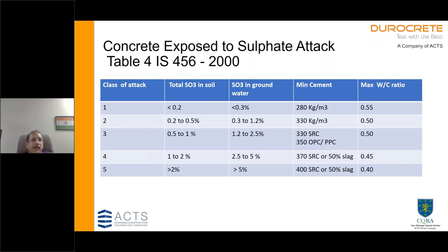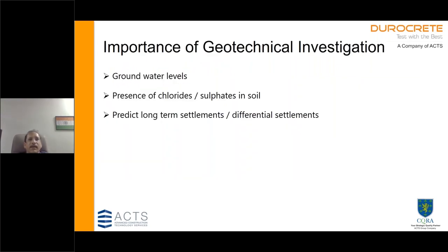Now many a times we find that there is a geotechnical investigation report, but the class of attack and the grade of concrete and the maximum water cement ratio is not taken in conjunction with the soil investigation report. If the SO3 content is between 0.5 to 1, they recommend either a sulfate resisting cement or OPC or PPC. And generally, if you are having a very high class 4 or class 5 level of sulfate attack, you need to either use a sulfate resisting cement, or if there's a possibility of a chloride attack, you should replace at least 50% of cement by slag and not use SRC. So these are the things that we need to look at. The importance of geotechnical investigation is very very important.